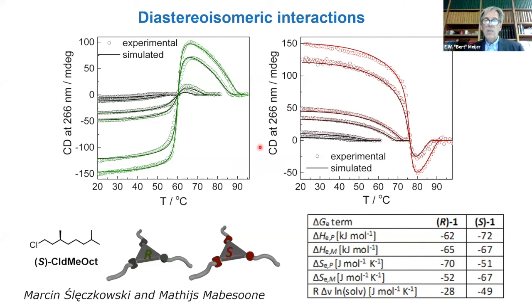So it's the solvent that makes a difference between the R and the S. And what you now see is that the effect is small, but due to the fact that you have a cooperative supramolecular structure that goes into hundreds of nanometers in length with the cooperativity, it's large enough to see the differences. But it also shows how important it is to not only look at the assembly of molecules and take the solvent as something that is just a solvent to dissolve the tails. It is really part of the assembly, which makes it very difficult, if you analyze supramolecular aggregates in solvents, to say what you're actually looking at. Are you looking at an ordered form of solvents around it, like what people say with water around the protein, or is it just the molecule that you're looking at? I think we have to do a lot in the future.